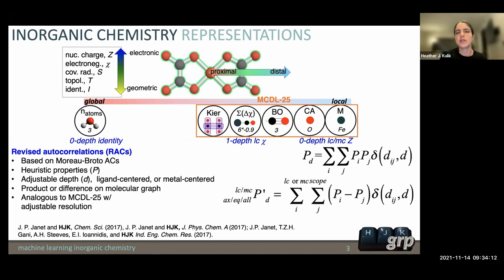Typically what we do is we come up with these pie charts where if the pie charts are a lot of blue, red, and green, that indicates a very metal local feature. Whereas if we see a lot more gray in this pie chart, like I'm showing here for redox, then that's a much more metal non-local feature. So what these two pie charts should show you is that you could design the spin of a transition metal complex while not changing its redox potential and vice versa, giving us opportunities for orthogonal design.